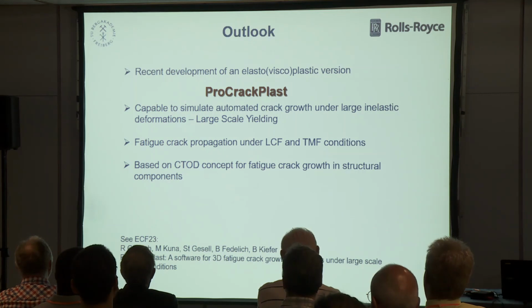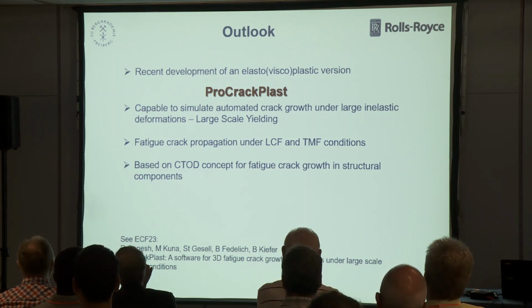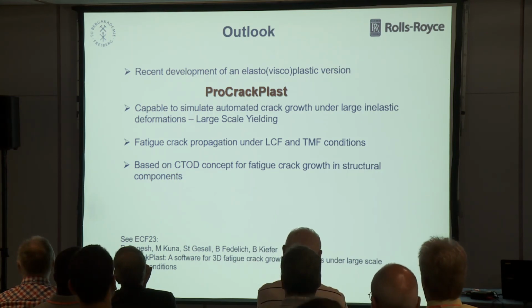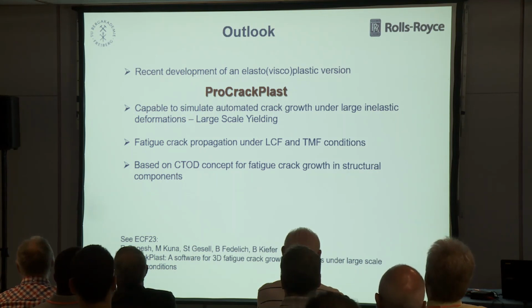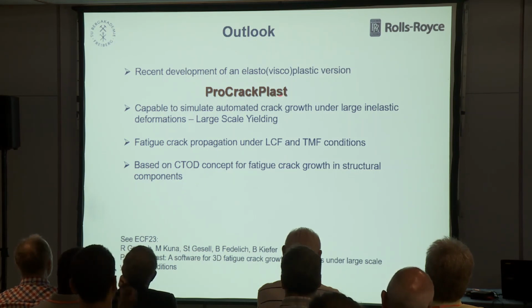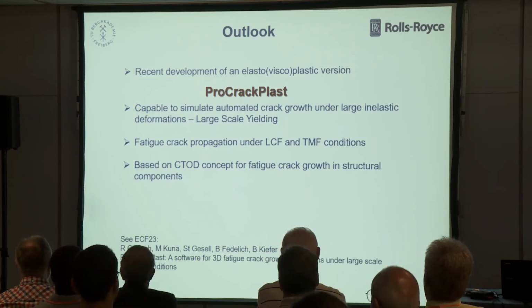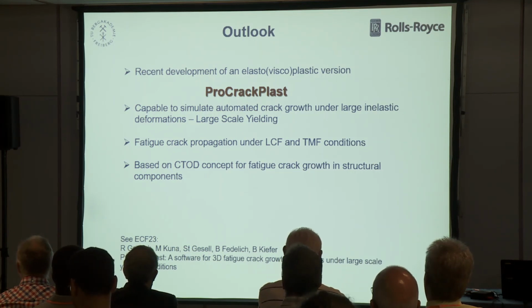So as an outlook, what I've shown here now is all resting on linear elastic fracture mechanics, delta K and K. In the case where the plastic zone becomes larger, with more deformation and creep, and more extended plastic zones, it would no longer be valid. So currently we are developing an extended version of ProCrack. It's called ProCrackPlast. Mr. Garnish has reported here in this conference on Monday, and this is now capable to tackle these large inelastic deformations. It means the plastic zones have to develop and be carried on with the propagating crack, and it is especially devoted to LCF and TMF applications.